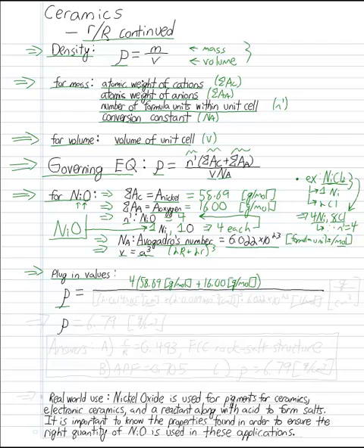All this is divided by 2 big R, 0.140 times 10 to the negative 7. This 10 to the negative 7th comes from being centimeters now as opposed to nanometers, so we converted. We're going to add to that 2 little r, 0.069. Once again, 10 to the negative 7th, since we want it in centimeters as opposed to nanometers.